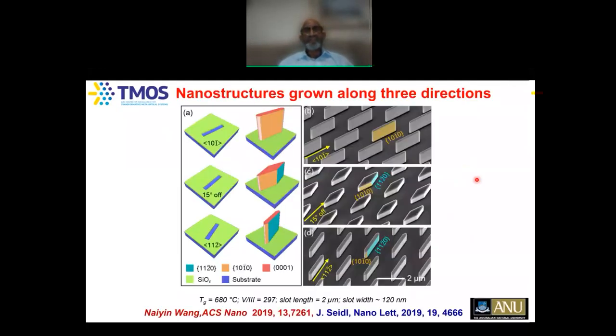Again, you can see that in this case, Naiyin Wang has opened this slot along a particular crystallographic orientation and then introduced it into the MOCVD reactor and heated it up to somewhere between 650 and 750 degrees Celsius. With the gases needed for the growth of indium phosphide, you can get beautiful, vertically standing nanomembranes here, instead of just nanowires, for example. And these membranes have this particular type of side facets.